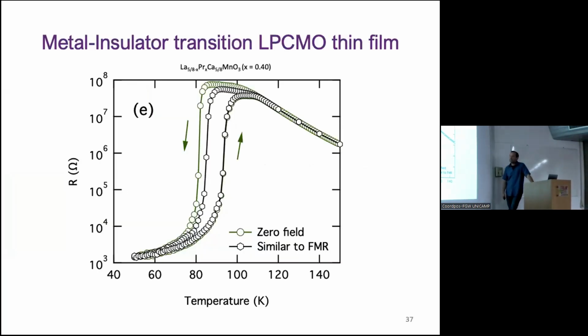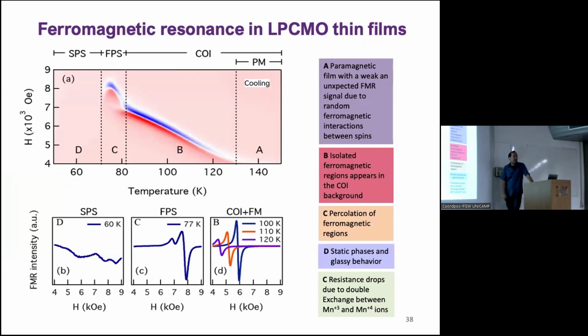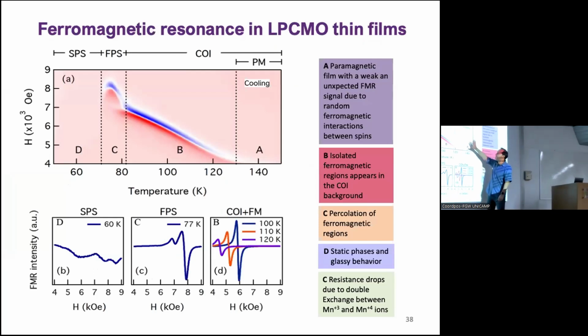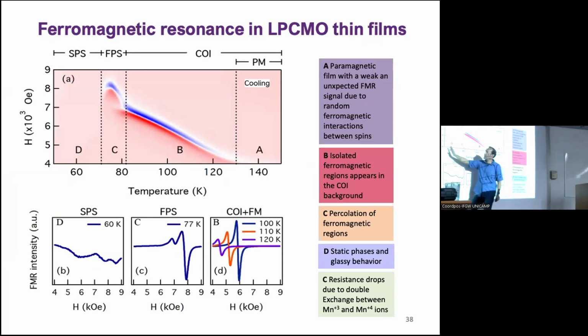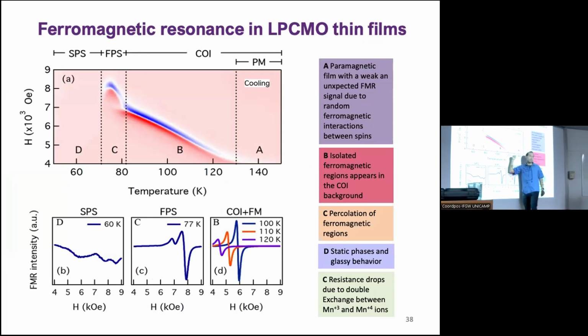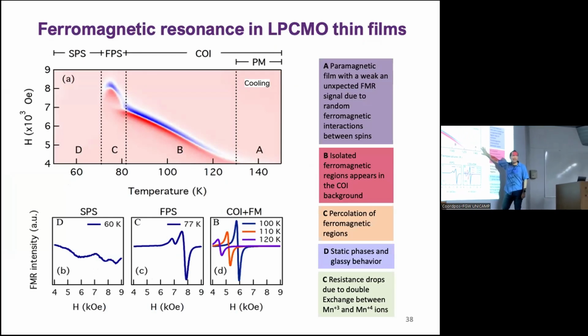So this is the metal insulator transition of this material. No field is applied here. The zero field is this one here. And then you see that there is a huge metal insulator transition happening in the material. This is the dynamics of the magnetism. Okay, so what I said before. So we have here, now this is field, and now this is temperature. Okay, so here we are in the paramagnetic region. So the signal that comes from here is just EPR signal. So it's just the electrons giving you resonances.